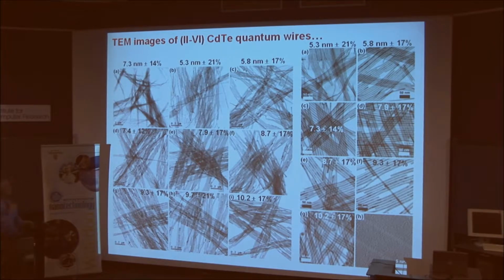Here are some TEM images of cadmium telluride quantum wires. You can see these look rather nice and uniform. You can also see that there's a strong tendency for these wires to align in parallel bundles when they're deposited from solution. So there are strong van der Waals and dipole-dipole attractions between the wires.